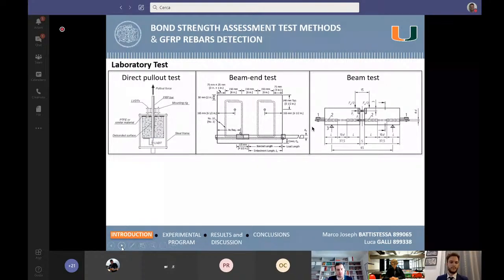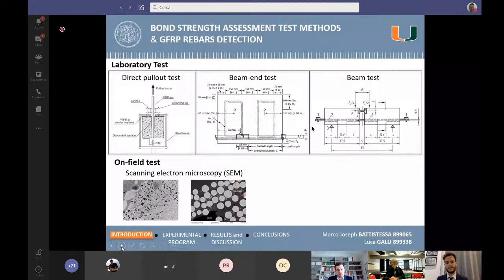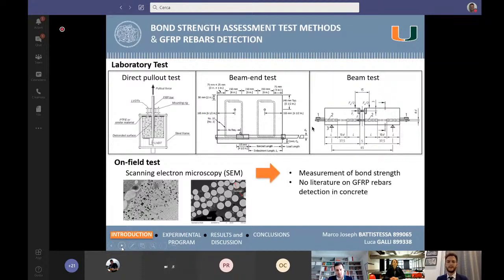However, these tests cannot be applied to specimens taken from existing structures. On the other hand, as an on-field test, scanning electron microscopy is the only way to observe the aging effect of GFRP rebars on specimens that come from a real structure. But of course, this test cannot measure the bond strength. So regarding on-field testing, there is a need for a way to measure the bond strength, and there is no literature on how to detect this kind of reinforcement inside the concrete.